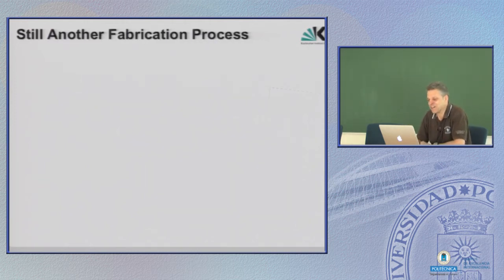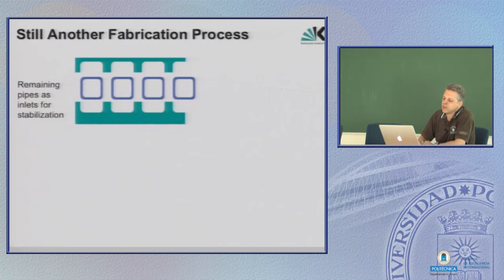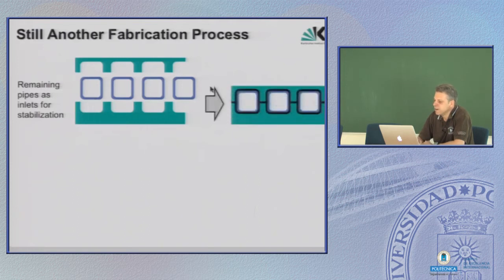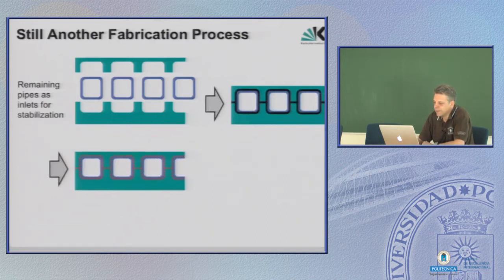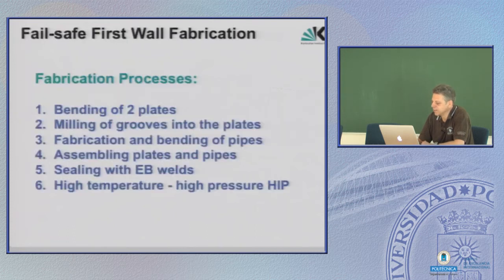But I didn't show you all the drawbacks, which in reality there are. You still have to take them into account, but I say in principle it works, and so we thought about another method, because if you do already all the work to fabricate these inlets, how about using inlets made of Eurofer with a thickness of 1 millimeter and leaving them inside. Or in other words, we thought about how to fabricate such pipes in the right dimension out of Eurofer, use them as inlets and leave them inside. These are several steps. You put them together, then again at the end and front you have to weld the whole thing leak tight in vacuum, press them together, and this is what we have done.